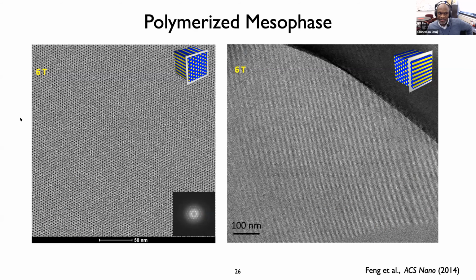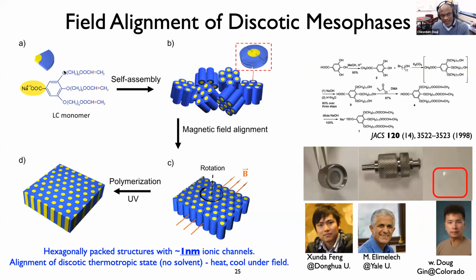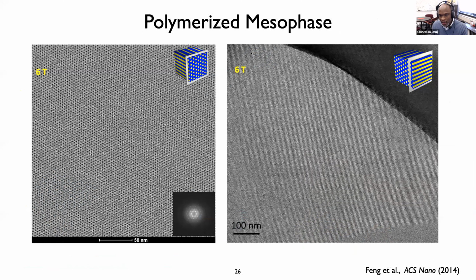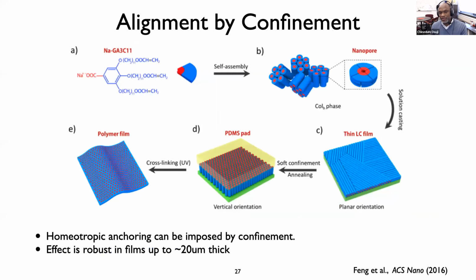So this is a transmission electron microscope image looking down the axis of those columnar channels and perpendicular to the axis of those columnar channels. And these are systems that were produced by orienting the sample using a large magnetic field, in this case, a 6 Tesla field, right? So this is a highly regular structure consisting of columns of these dendron-shaped molecules that have come together as disks. And at the center of each of those columns is a 1 nanometer pore that offers a potential for nanofiltration.